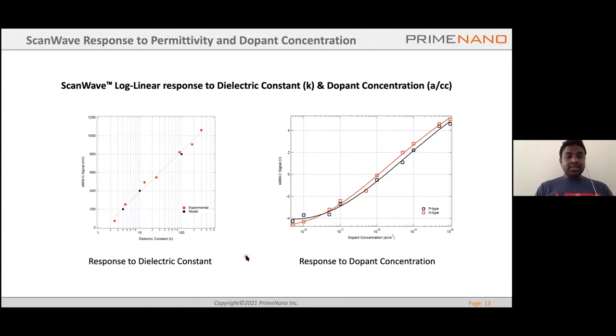In this graph, I'm showing the ScanWave response, the capacitance response, with respect to varying the permittivity of the sample or looking at the variation in the dopant concentration. On the left graph here, I have on the x-axis the dielectric constant varying on a logarithmic scale, and on the y-axis, I have the sMIM capacitance signal experimentally recorded. As you can see, with the variation in the dielectric, the response is almost linear. This helps in identifying an unknown dielectric constant material. If you have a reference of at least two points of known dielectric constants, you can interpolate, and also extrapolate to other areas, as the response is almost linear.